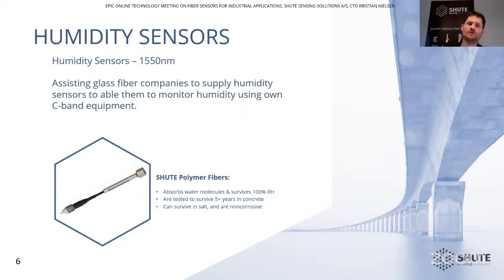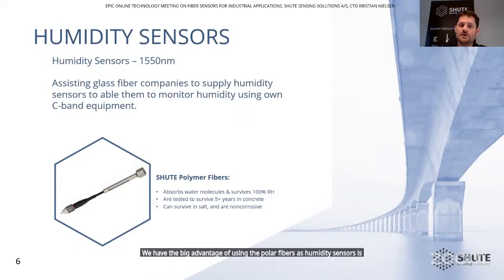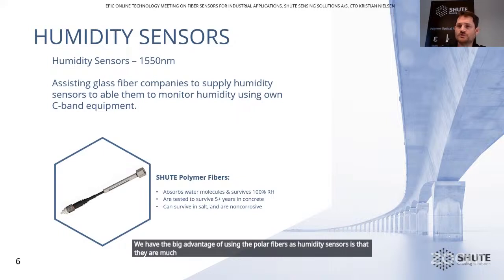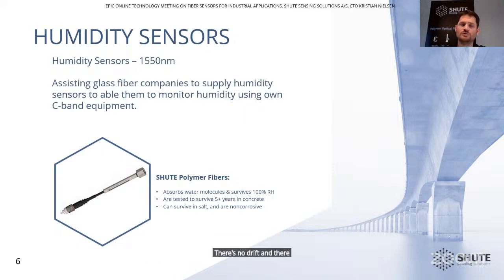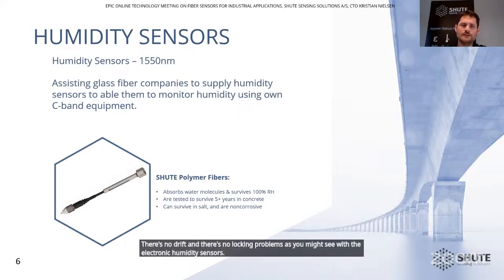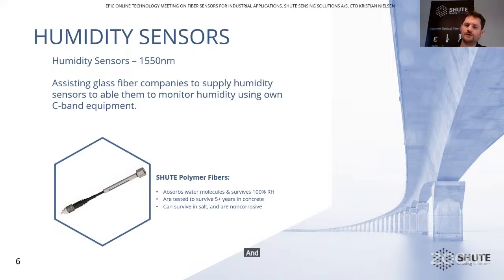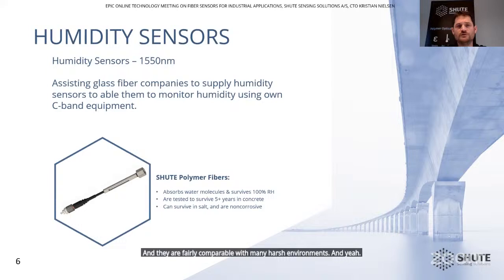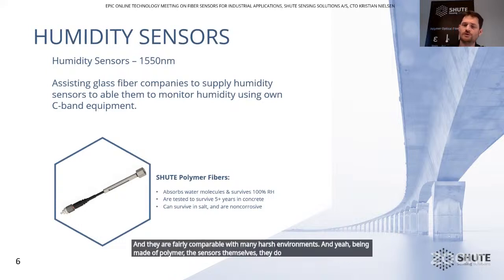The big advantage of using the polymer fibers as humidity sensors is that they are much more robust with regards to very high humidity levels. We can leave them in water for months, and afterwards they will still function after they have dried off. There's no drift and there's no lock-in problems, as you might see with electronic humidity sensors. And they are fairly compatible with many harsh environments. Being made of polymer, the sensors do not corrode and they do not conduct electricity.